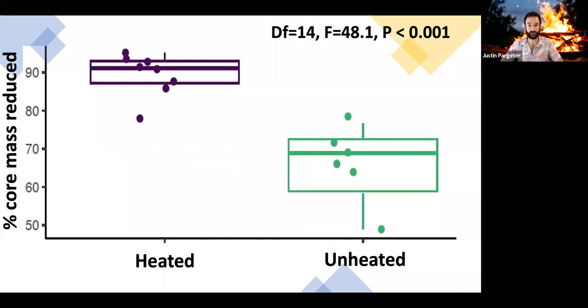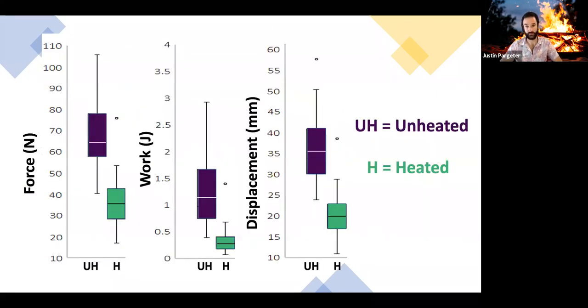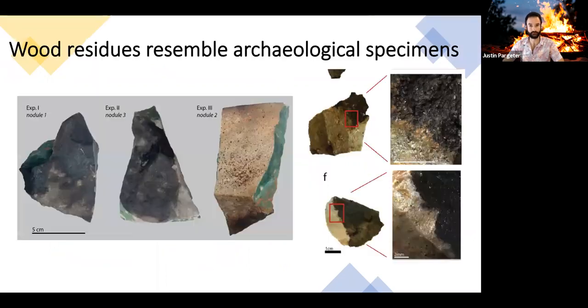Our second results showed that surface fire heat treated cores are significantly smaller and offer greater utility on average than unheated cores. Our sharpness tests show significant differences between the heated and unheated silcrete flakes in terms of the force, work, and displacement when slicing through the PVC tube. When flakes are fresh and at their sharpest, heat-treated flakes require roughly half as much force and about 1/3 the energy to cut through the PVC tube.